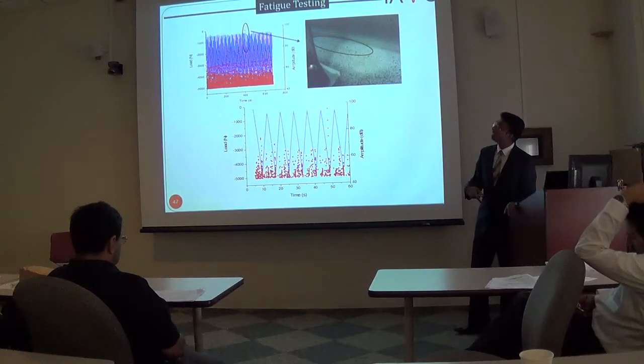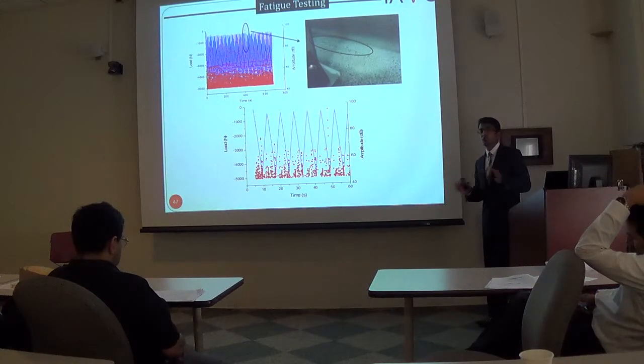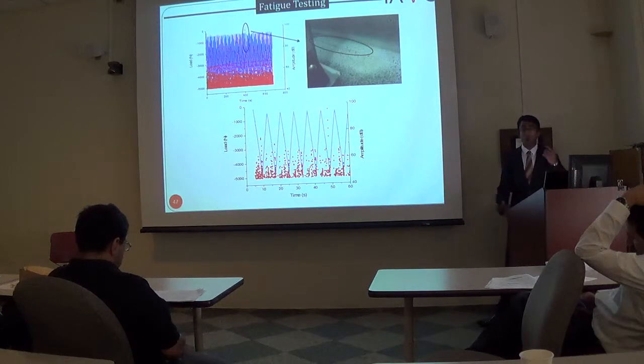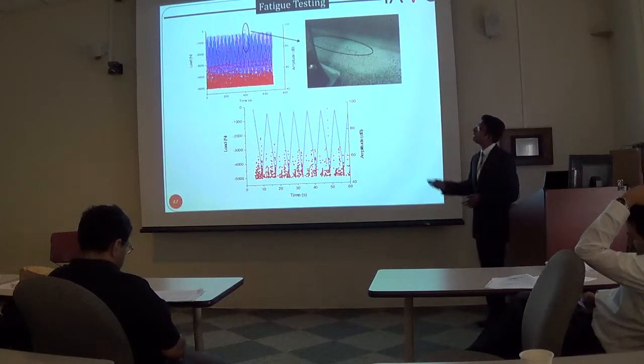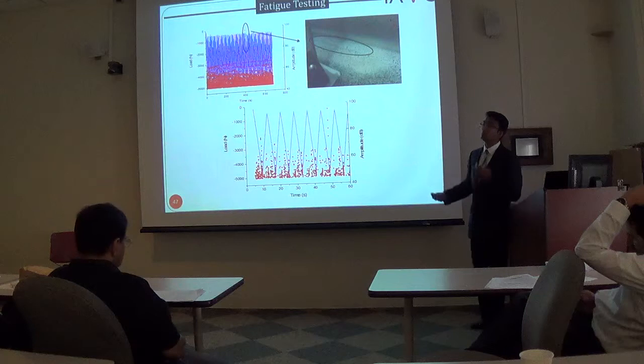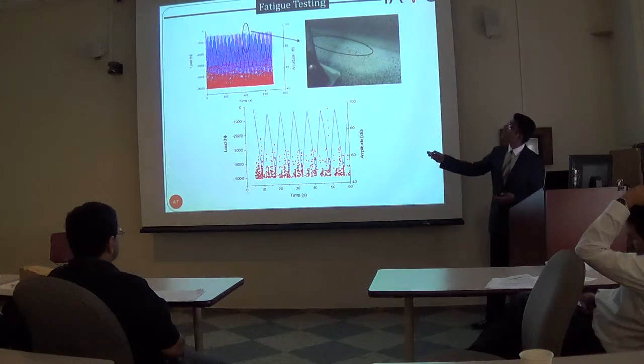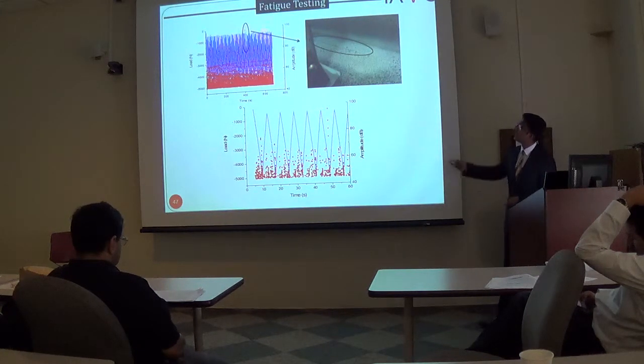So in the quasi-static specimens, there was no visual debonding that was identified, but there were a lot of audible signs that were picked up. But in the fatigue testing, we could actually see visual signs of debonding, which corresponded to high amplitude AE signals as seen here.